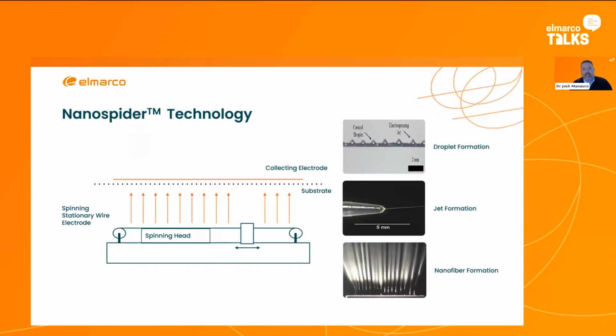So about the nanospider technologies, Tom started to briefly touch on it. If you're familiar with our technology, this will just be a review. In our standard equipment, and I have a video to illustrate this a little bit later, we have a coating head. It's a coating technology. Normally, we're coating onto some substrate that could be a nonwoven, a paper, a film, something like that. We're passing that film in between two electrodes, the spinning electrode and the collecting electrode, and that substrate gets in the way between those two electrodes, and the fibers are attracted to the collecting electrode from the spinning electrode, and they collect onto the substrate and form anywhere from fractions of a gram per square meter for some air filtration applications, up to 10, 15 grams per square meter for membranes, let's say, breathable hydrophobic membranes or separators or anything like that that would actually require more of a membrane.